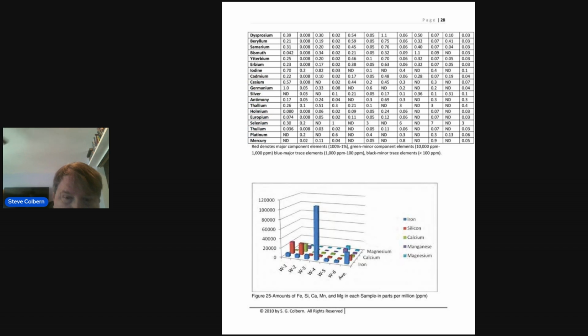Yeah, we have dysprosium. Dysprosium and I think it was ytterbium were present in those brown dots that we thought might be mechanical actuators on the honeycomb sample I mentioned. And europium, there's quite a few rare earths in here. A little bit of erbium, a little bit of iodine, samarium. Yeah. Very strange.